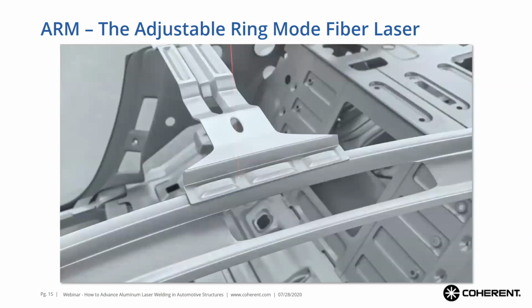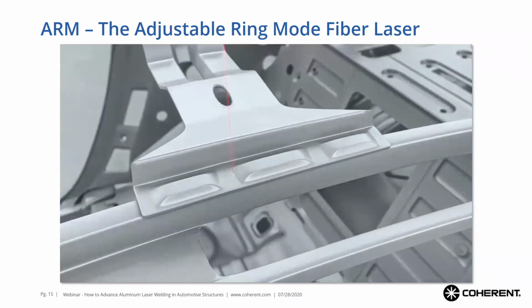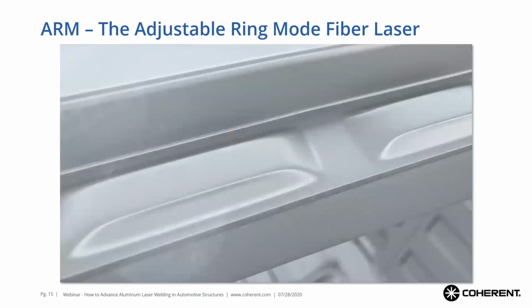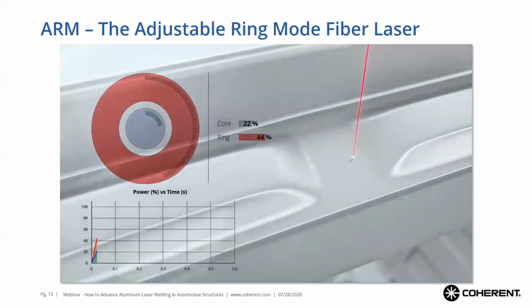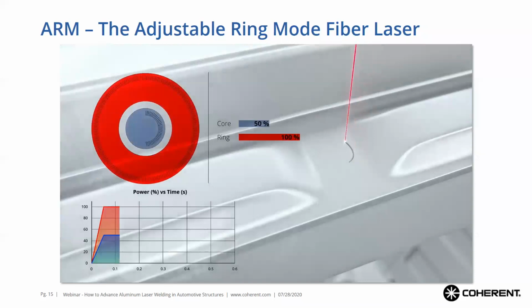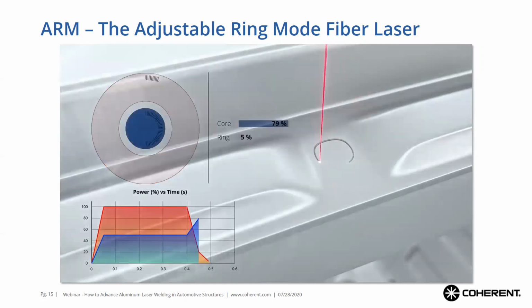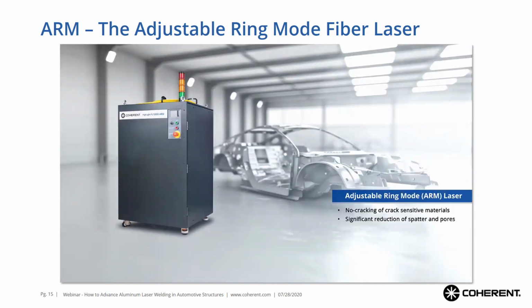Next, we're going to demonstrate an actual application on a vehicle. So this is an example of a remote weld, which is very common in the automotive industry. And you can see from the chart on the left, at the start, you can ramp them individually. Then you go into a steady state mode. And then a lot of the problems occur at the tail end of the weld. You can ramp them down individually to avoid issues in your weld termination. And in the end, you can eliminate the cracking, and you can have a significant reduction in spatter as well as pores.